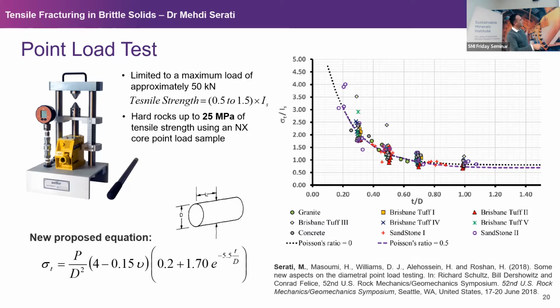And where you see in this chart, the prediction of this equation is plotted for you with the dashed line, one for Poisson ratio of 0 to get the spectrum, and one for Poisson ratio of 0.5. The dot points here are also experimental results. So hopefully you agree, given that it's an index test and you just need to get an estimation, there is no way that you do a point load test and get very precise measurements of tensile strength. Hopefully you agree with me that there is a reasonable agreement between the prediction of this equation and the experimental results.